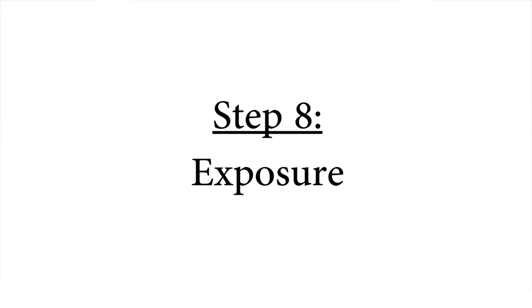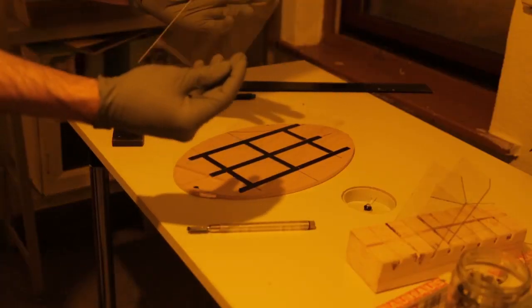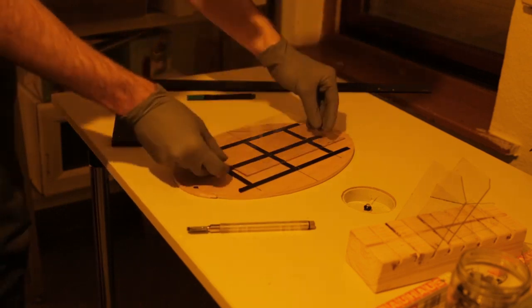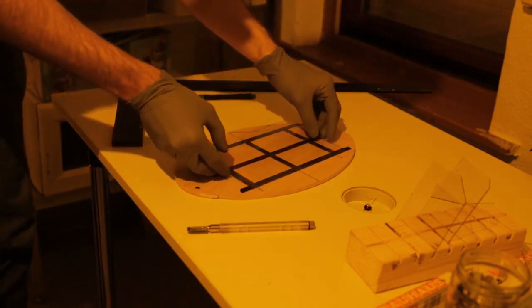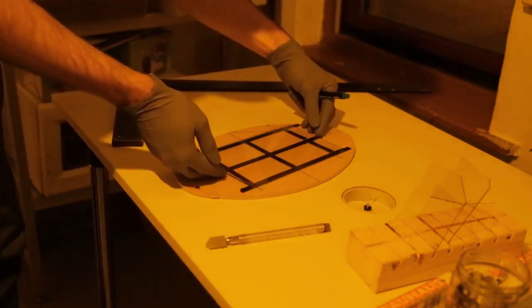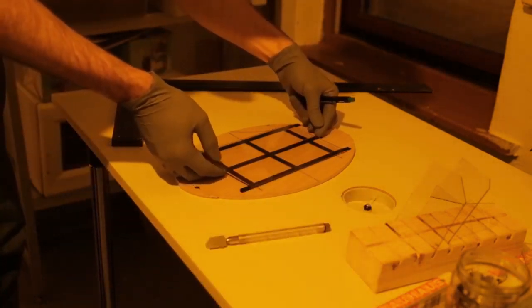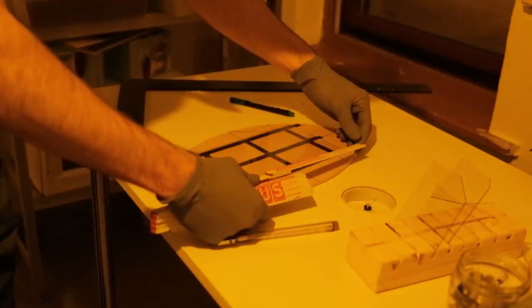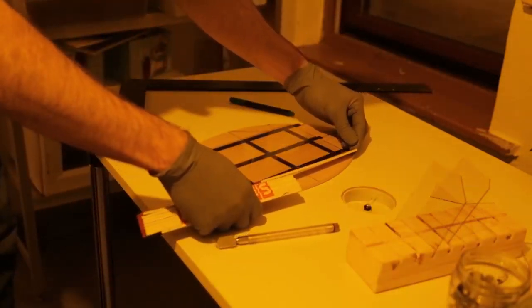Step 8. Exposure. To maximize efficiency, I coated the plates in the biggest size possible. Now I have to cut them up. First, I recheck the coating job and the glass quality. Sometimes it's necessary to clean the uncoated side with window cleaner. For this hologram, I've coated very thin glass. It's only 2 millimeters thick.